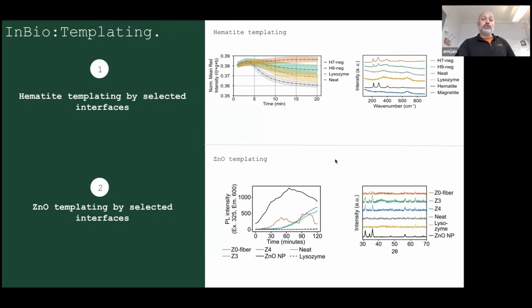But when we added our two unidentified proteins, H7 and H9, we saw some effect with the H7 doing kind of a crazy effect. I was amazed to see then that if we look with Raman on the output of these experiments, so here at the bottom you have the fingerprint of standardized hematite and the fingerprint of magnetite. And I was amazed to see that the lysozyme and the NEAT looked spot on the magnetite, and the H7 and the H9 that were selected with the hematite nanoparticles gave something that really looks like hematite. So I was quite happy and excited about this.